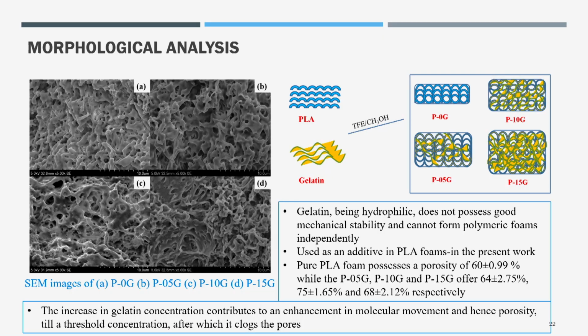I will show you. Morphology was the most interesting thing. You can see that the left-hand side's morphology is the 0 system, no gelatin. The right-hand side is 5 gelatin. Down left is 10 gelatin, and down right is 15. If you scan carefully, with very acceptable pores depending upon the drug dimension, P10G happens to be better. From our other experimentations also, P10G contains a lot of uniformly distributed pores compared to other systems. You can see that.